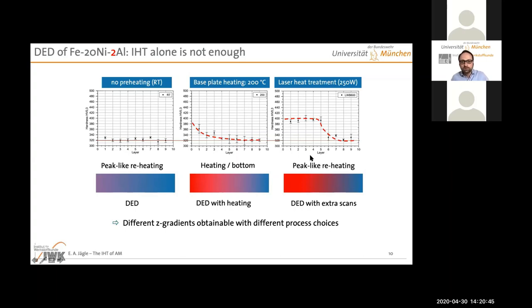You could also use the laser as an additional heat input. So here, colleagues at Fraunhofer did an experiment where they first deposited the material, and then they went over the material a second time with the laser, but this time with way less power. So this is not remelting the material. This is just giving it another temperature peak, basically. And you can see that we suddenly have this higher hardness at the bottom. But then towards the top, we have a relatively sharp drop. And this again has something to do with the number of reheating peaks. And we will look at this kind of behavior a bit more in detail in later slides. So depending on what you do, with heating from the bottom or with reheating with a laser, you can in principle generate different hardness profiles in the material.